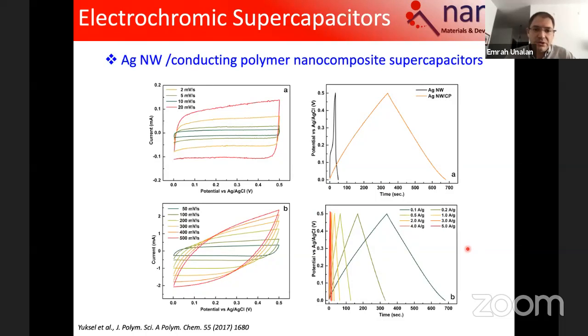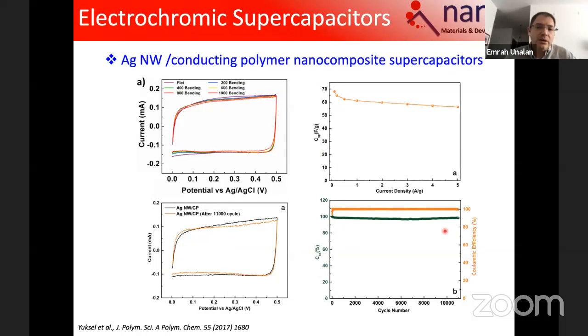So they can charge and discharge and can do this very many times, and they can hold very large current densities. But again, the storage is low, so you're below 100 farads per gram, where in fact you can get more than thousands with the metal oxides, and with the carbon you can typically get around 200, 250 if you have very large surface area carbon.